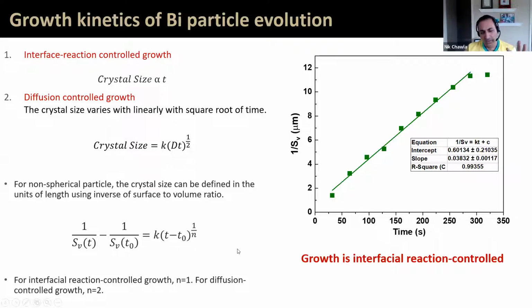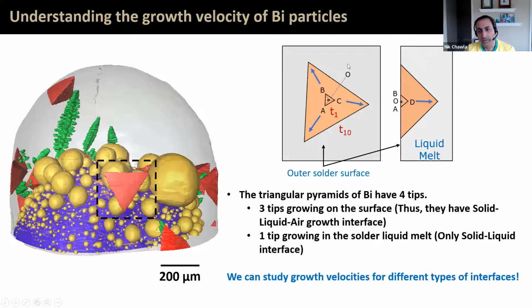So this is really the beauty of tomography, because we can get time-dependent measurements and we can fit them to either existing models, or we can refine or come up with our own models. But the nice thing is we have 3-dimensional time-evolved data, and in this particular case, it's crystal size versus time. Okay, and finally, you can do things like measure the growth velocity. So this is also some work in progress.